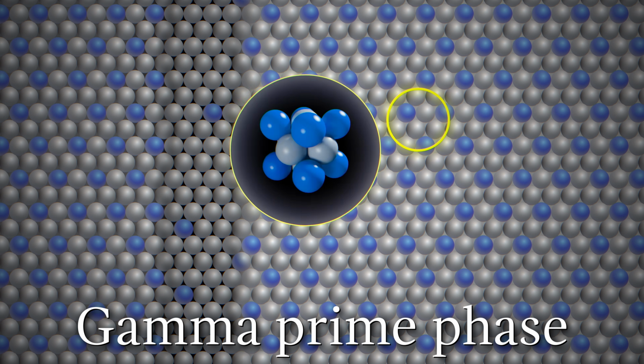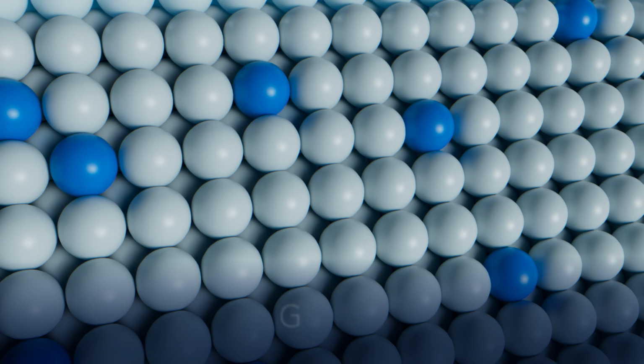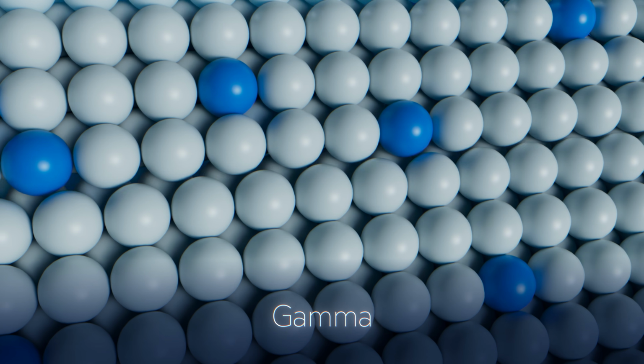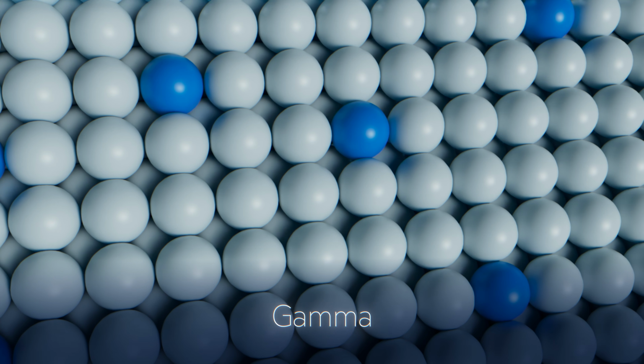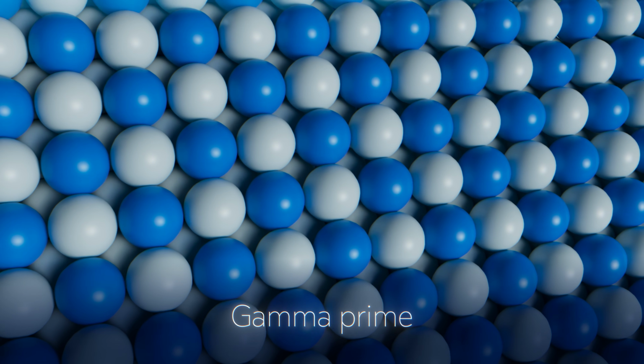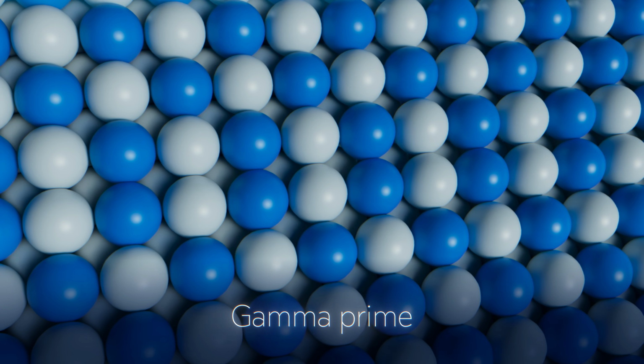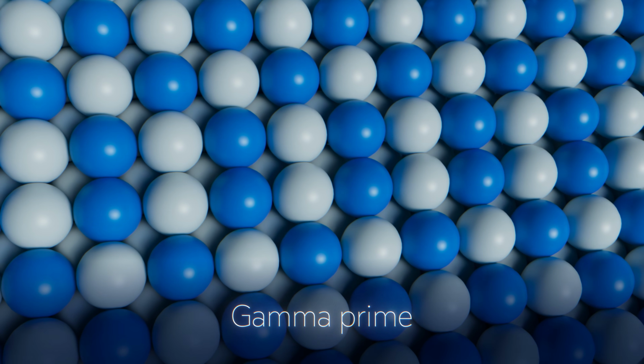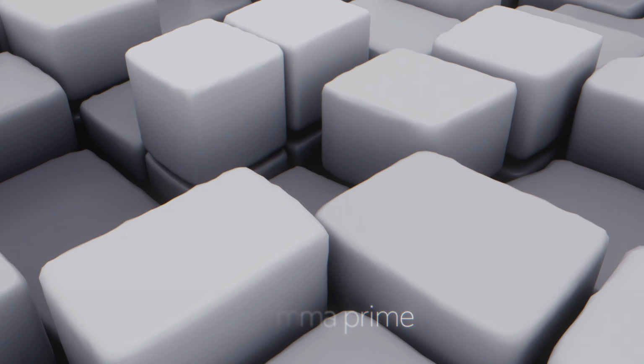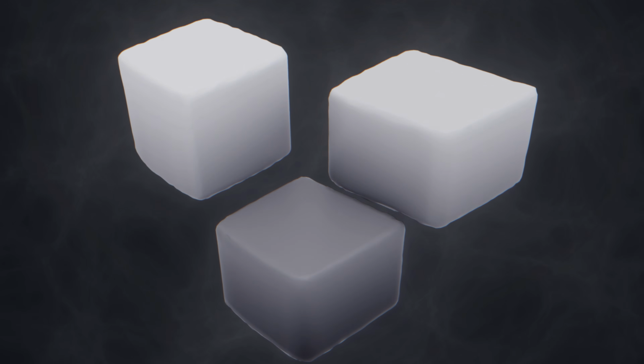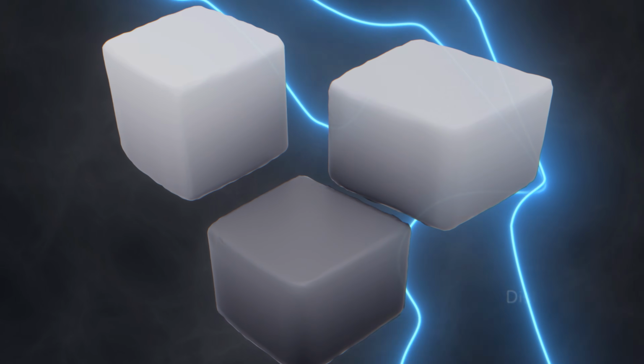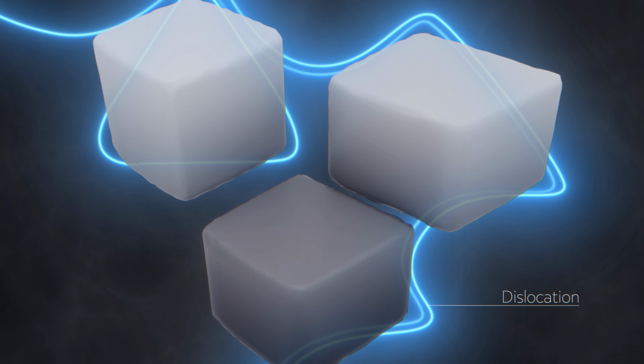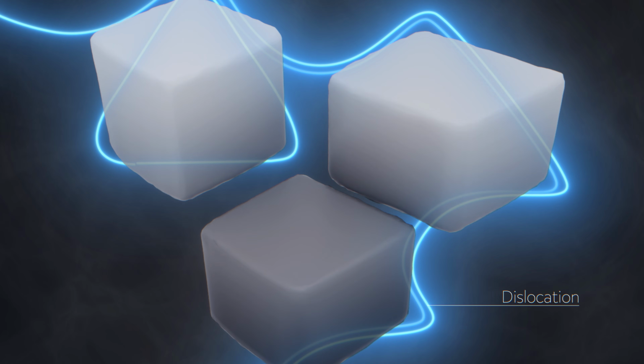And it's this difference that is crucial when a dislocation tries to glide through the lattice. In the roads, this motion is easy. Each layer of atoms can shear smoothly past the next, leaving the structure looking unchanged behind it. But if you try to do the same thing in the blocks, well, now you're actually changing the order of the atoms. Nickel and aluminum end up sitting in the wrong places. That takes energy, so the lattice resists it. So when a dislocation moving through the roads hits a block, it gets stuck. And that's what makes this alloy so strong.